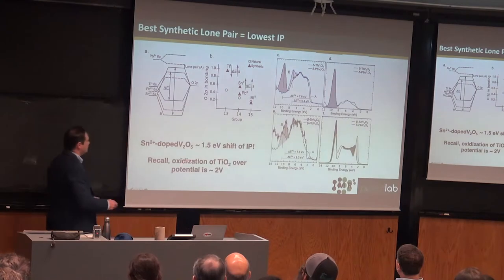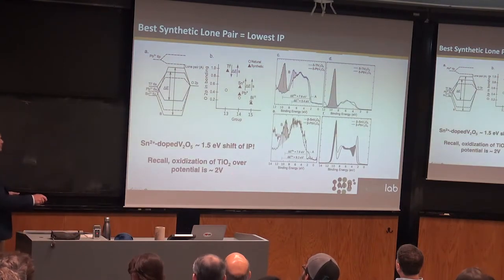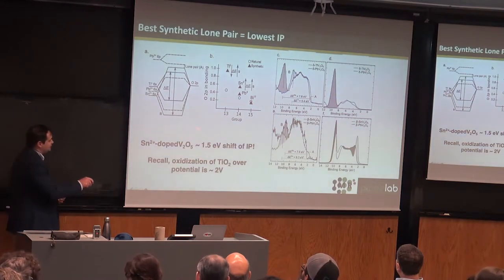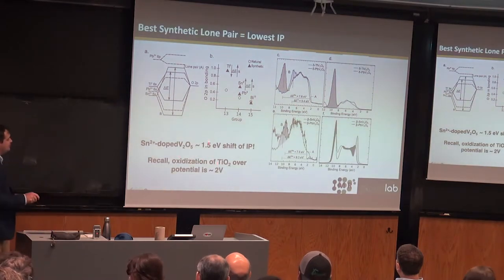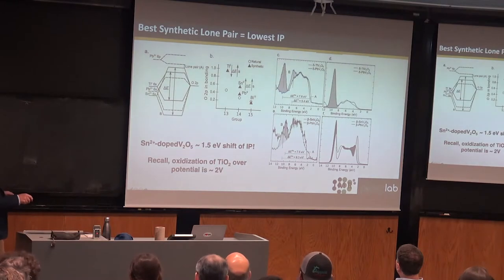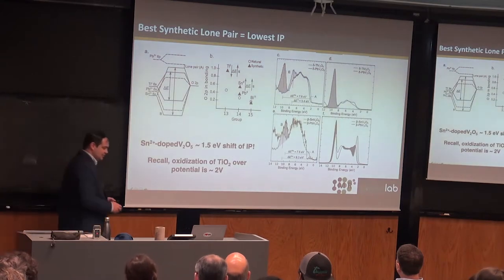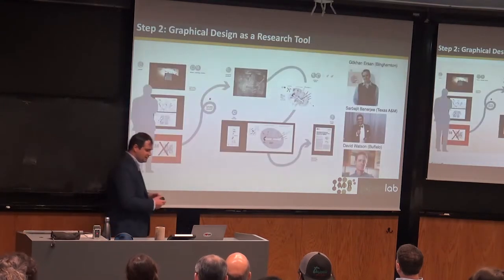Because remember, our oxidation overpotential for TiO2, which was oxygen 2p derived, valence band was about 2 volts. Undoped V2O5, similar-ish order of magnitude overpotential would be required. And so you're talking about a 1.5 shift in ionization potential. That's really cool.